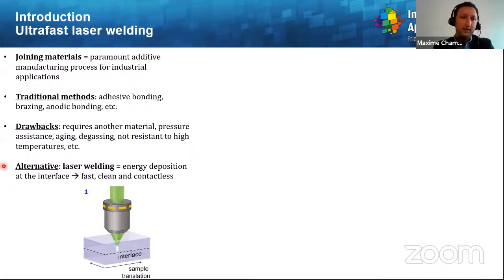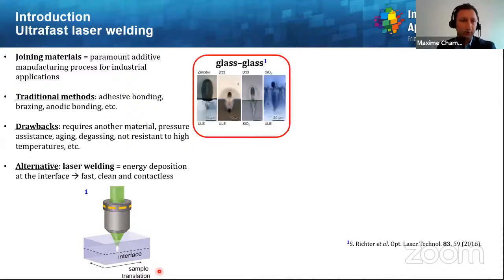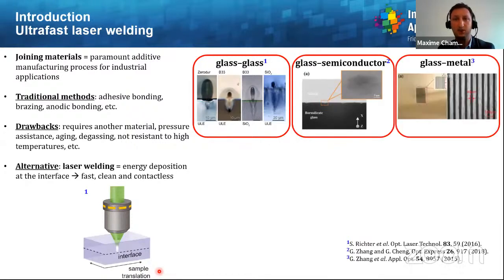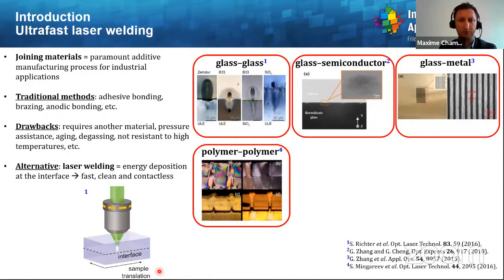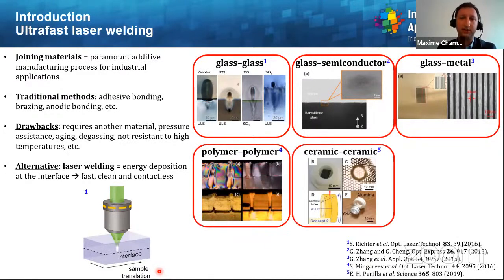As a quite nice alternative, the laser welding technique has been developed, which consists of an energy deposition at the interface, as illustrated here, and it provides a fast, clean, and contactless way to join materials with a high strength between those. It was shown to be applicable in different material configurations, such as glass-glass, glass semiconductor, glass-metal, polymer-polymer, and more recently, ceramic-ceramic, as demonstrated in this science paper in 2019.